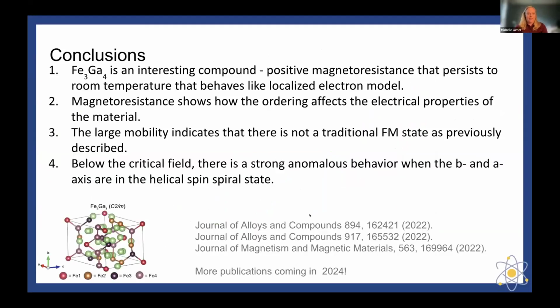So hopefully I convinced you that this is an interesting compound. The positive magnetoresistance persists almost to room temperature, and it behaves like a localized electron model. And what we notice is that the magnetoresistance really shows how the ordering affects the electronic properties of the material. So in addition, there's also the super large mobility, which at low field, low temperature, is not necessarily a traditional ferromagnetic state.